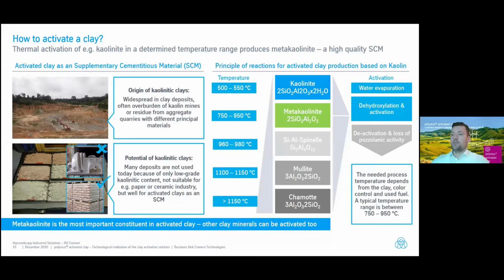So first of all, the clay must not be of a very, very high quality. This is not needed for activated clay production. So we don't need the high kaolinite content as you need it for ceramics production, for example. This would be far too expensive, and we don't need it for the cement quality. What we need is what I just told you before. So something with a kaolin content between 20 to 40% would be good, and a certain chemistry accordingly.